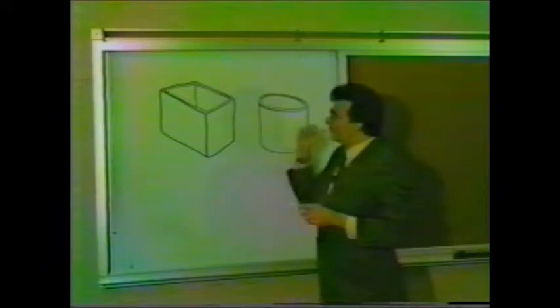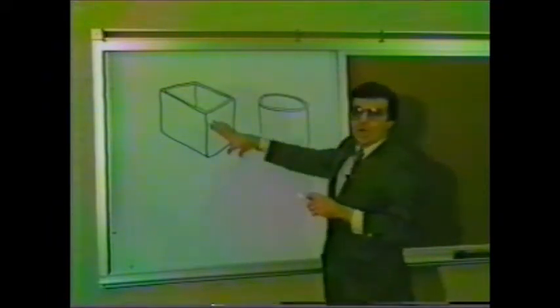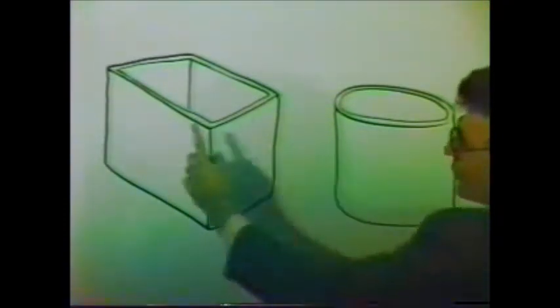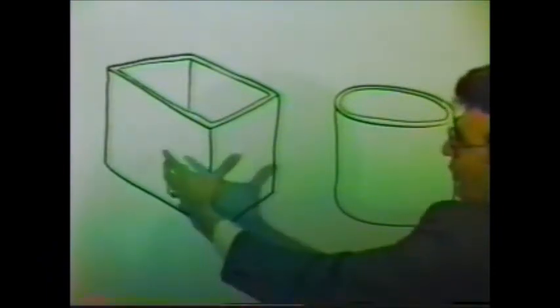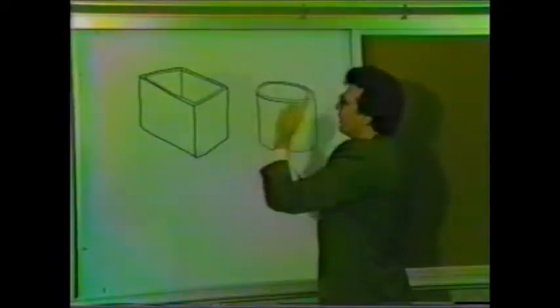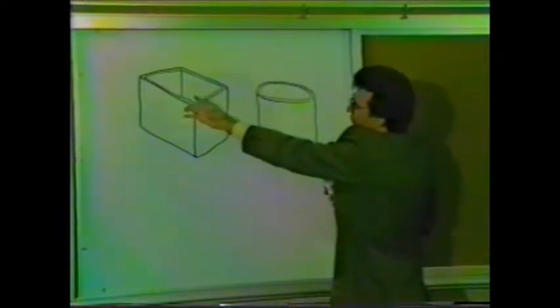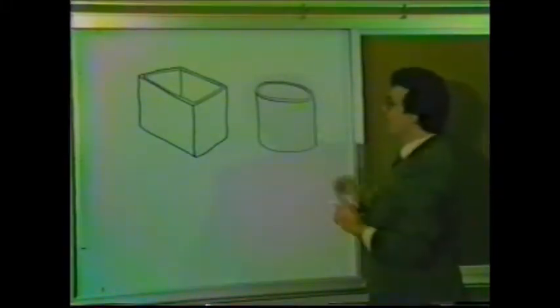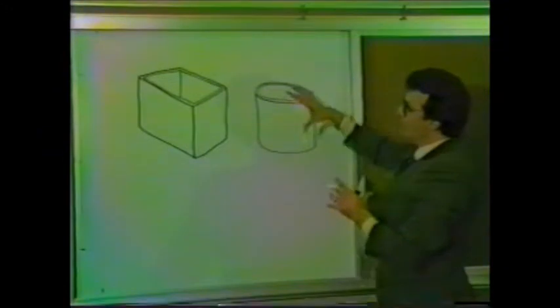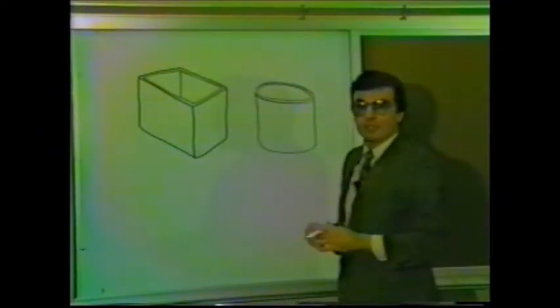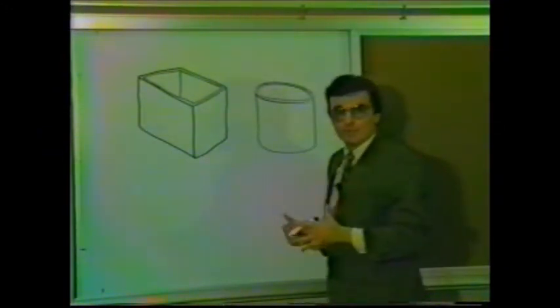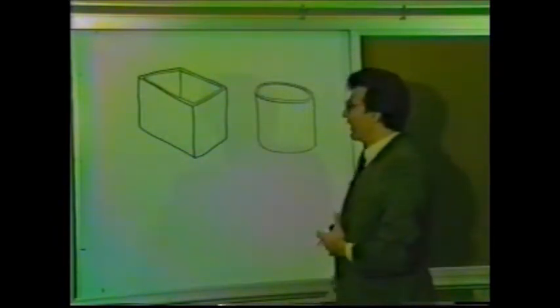And the basic difference between the two pertains to how the steel solidifies. There is an optional process called electromagnetic stirring, where you can actually stir the liquid steel within the mold before it solidifies. That can be done with a rectangular mold or a square mold. With a round mold, you can actually spin the mold to accomplish the same effect. And the basic effect of either spinning the mold or using electromagnetic stirring serves to homogenize the structure of the steel as it's solidifying.